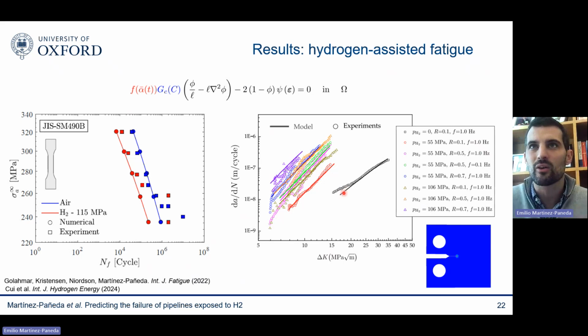So the same model you're using for this result in air is the same one here. We just change the way we load our sample, whether we load faster or slower based on this frequency. We change the pressure using Sievert's law. We change the concentration of hydrogen that we put on the surface. And then we change, of course, the loading ratio as well. So it's all playing with the loading conditions, but we are not touching any of the parameters involved in the model. So these are all very rigorous predictions.